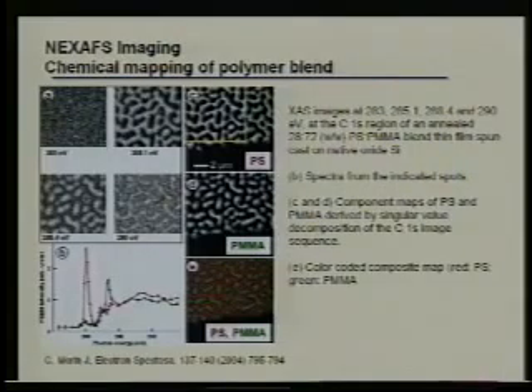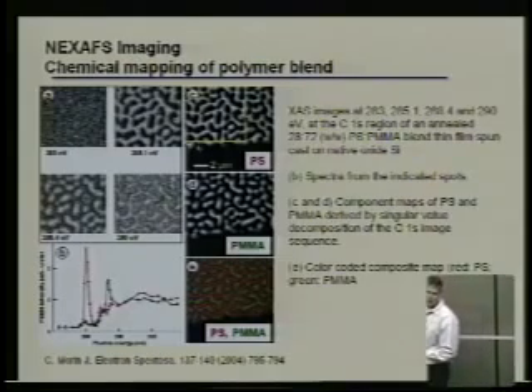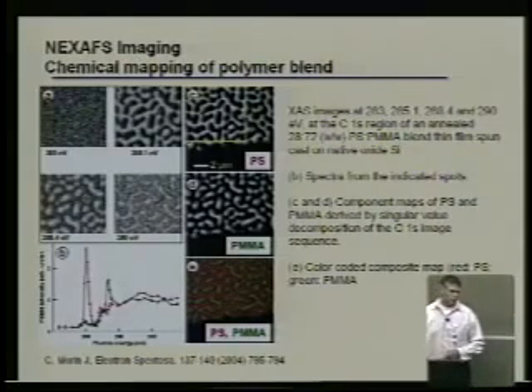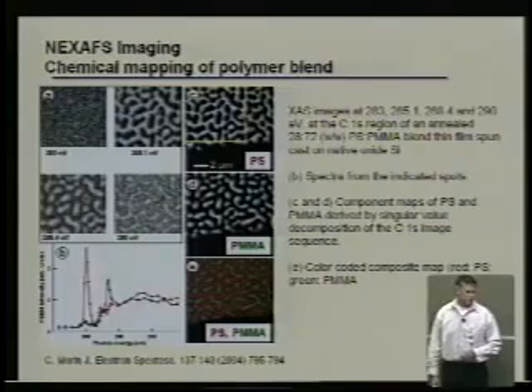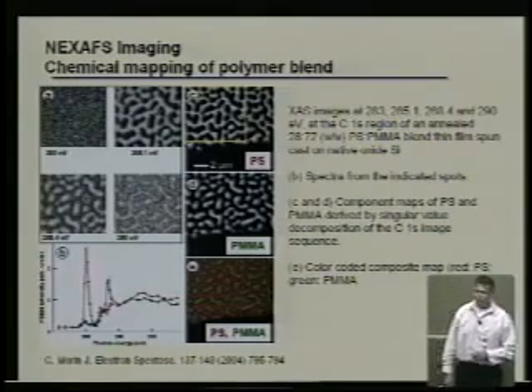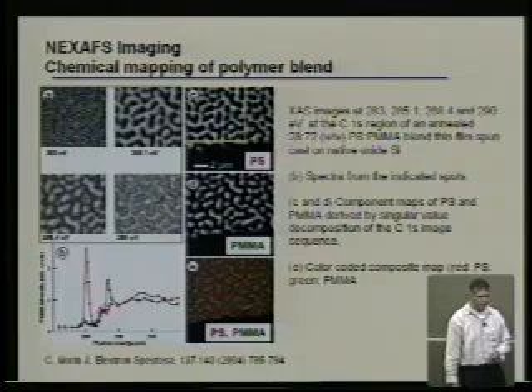But another nice thing is you can do chemical mapping. So what I've shown here is a combination of two polymers, polystyrene and polymethyl methacrylate. And what I've shown here in plot A is the contrast in the polymer blend as a function of excitation energy. This is work done in the group of Adam Hitchcock.